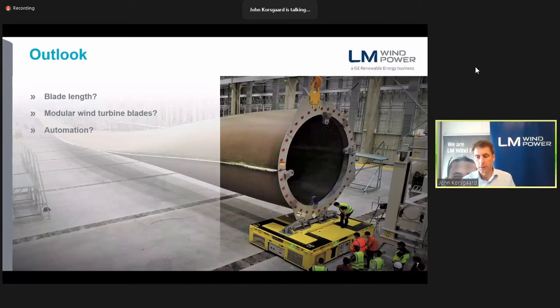For onshore wind turbine blades, transport of blades from plant to site is an increasing challenge, especially to locations with complex accessibility. To overcome the logistic challenges, segmented blades have been introduced, and we have developed such a segmented blade concept. With that, new opportunities for alternative manufacturing processes have been investigated, especially for the tip part, because that is now a quite smaller part, still in the size of 20 to 30 meters we envision, while the inner part will still be produced in the same state-of-the-art manner as we produce a single piece blade.